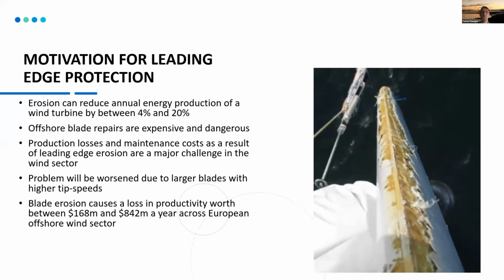And the next one is much more closely related to some of what Ian was talking about, Professor Hamerton, on leading edge erosion. So we found some papers that said that erosion causes losses of between 4 and 20% of AEP. I think 20% is probably a bit high, but in environments where it's hard to service the blades, particularly offshore, it's a problem. Also, again, offshore blade repairs become dangerous and expensive, and you've got issues with weather windows. And as the blades get even bigger, it becomes even harder to service.